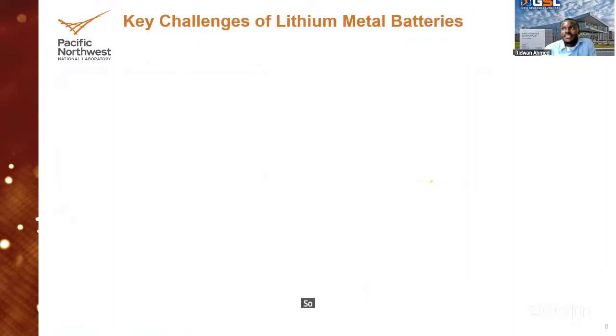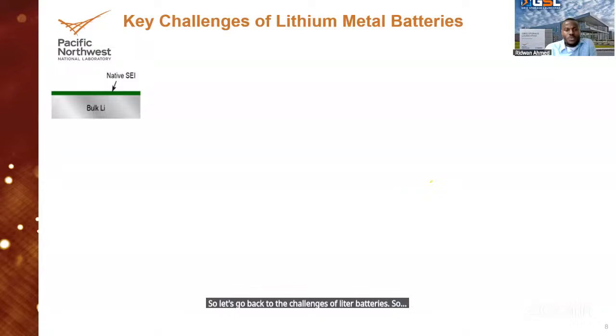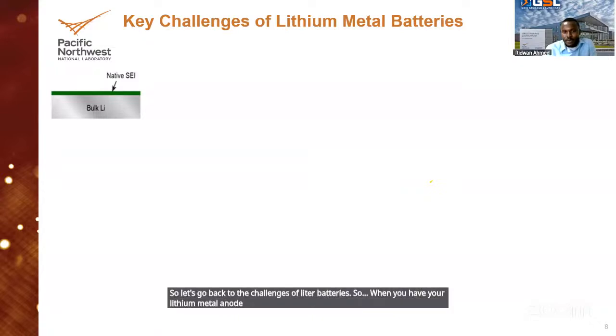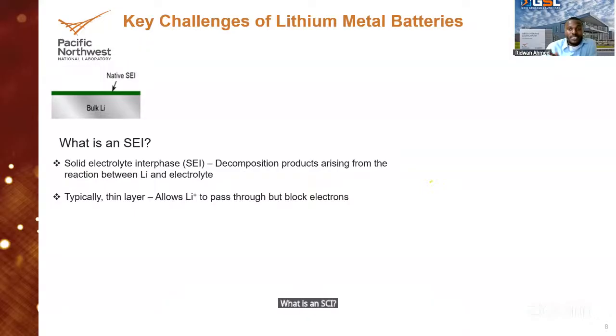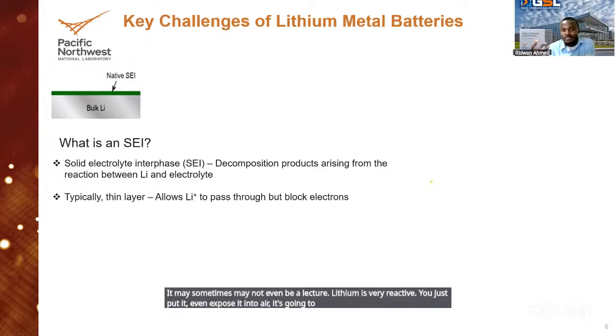So let's go back to the challenges of lithium metal batteries. When you have your lithium metal anode, the bare or bulk lithium usually has a thin layer on top of it, which is a decomposition product. We call it SEI. What is an SEI? Basically, SEI stands for solid electrolyte interphase. That's the decomposition products arising from the reaction between lithium and electrolyte. Sometimes it may not even be electrolyte. Lithium is very reactive. You just expose it to air, it's going to react, and you can have components like lithium oxide and all sorts of things forming on top of it.